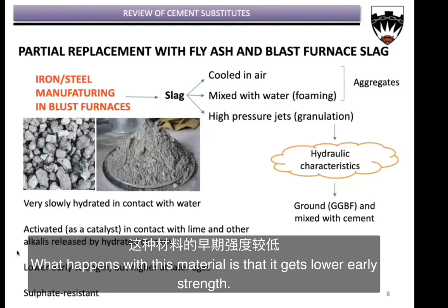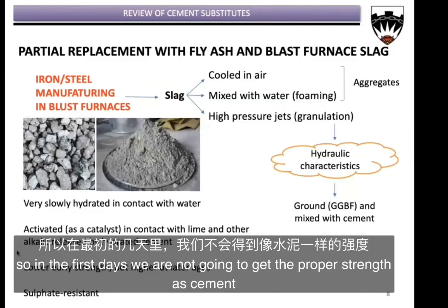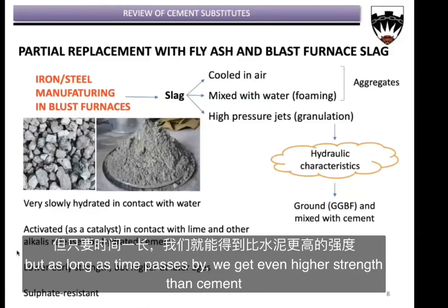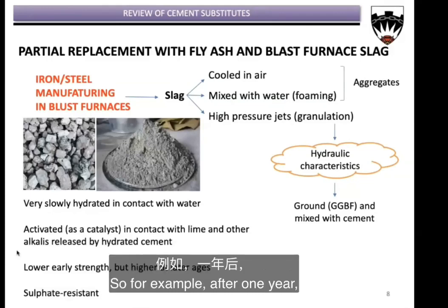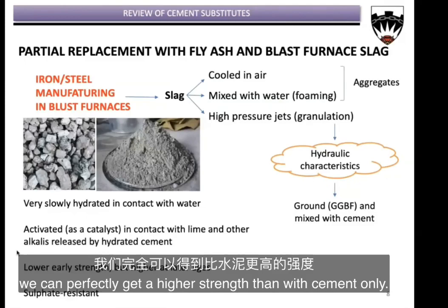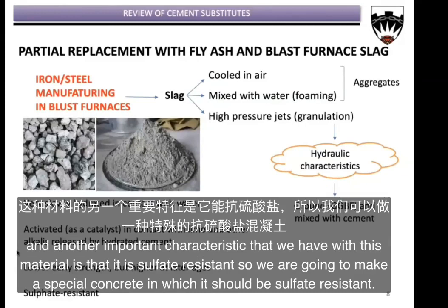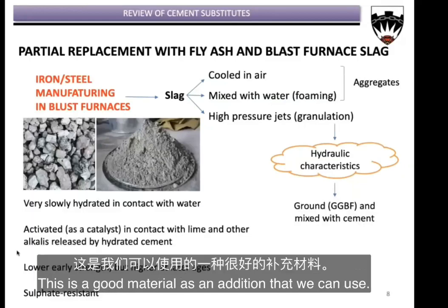What happens with this material is that it gets a lower early strength. So in the first days, we are not going to get the proper strength as cement, right? But as time passes, at longer ages, we get higher strength than even cement, right? So for example, after 1 year, we can perfectly get a higher strength than with cement only. And another important characteristic of this material is that it is sulfate resistant. So if we are going to make a special concrete that should be sulfate resistant, this is a good material as an addition that we can use.